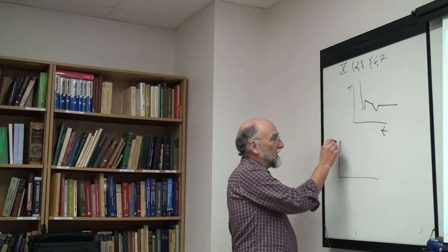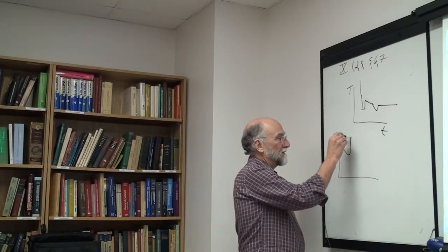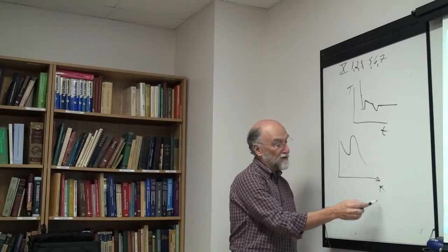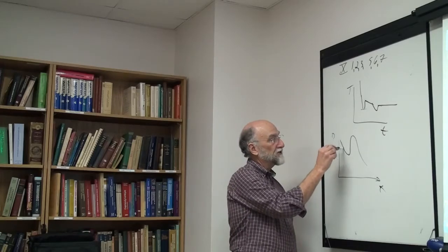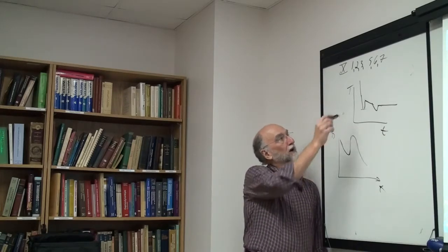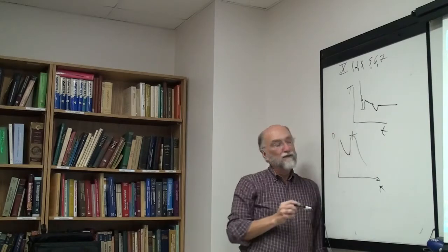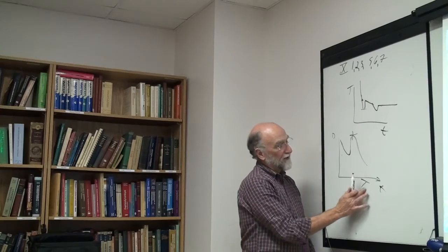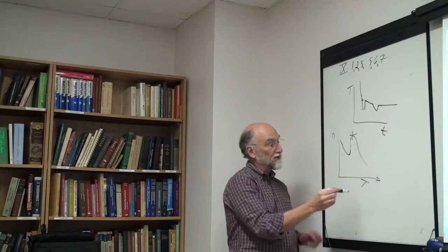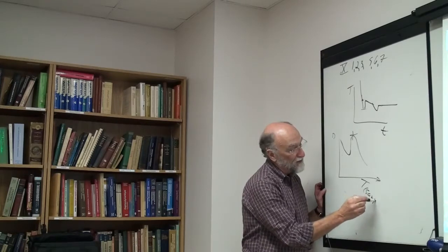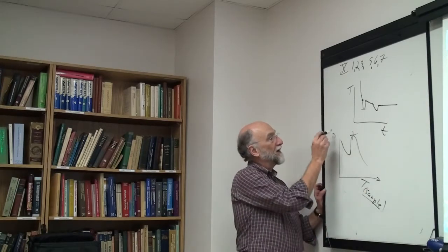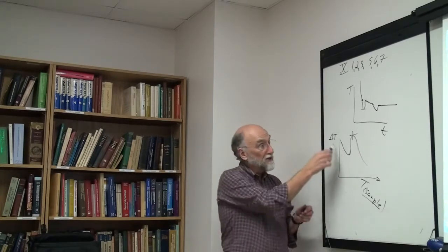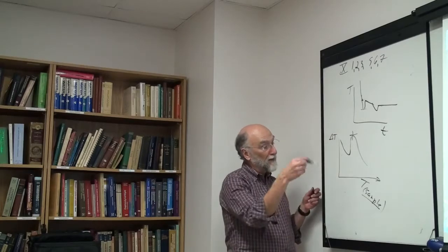What do you see? You cool the thing down, and then you get a peak. This is the heat. This is an exothermic peak. This is your time here. This is the temperature of the furnace. And this is your DTA signal, so you get a peak. So where then do you take your liquidus? People will take this to be the liquidus. This is your temperature of the furnace, T, where you're measuring temperature and then you're measuring the DTA signals. So this is T of the sample. One thermocouple is measuring the T of the sample, and this is your delta T between your sample and your reference. Okay, so you see the effect going on here. The idea is you magnify the effect, and so on.